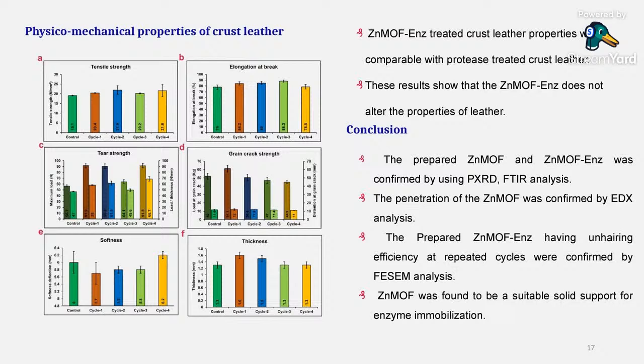Now what we are doing is, can we use a different system in one shot at higher pH? We don't want to go back and forth with pH variations, because in the initial process of unhairing, we will be changing the pH from 4.5 to 9.5. Instead of going to higher alkaline pH and coming back to pH 6.5, can we have a highly stable metal organic framework which can withstand the higher pH? Then can we use that material for our enzymatic process? That is what we are currently working on.